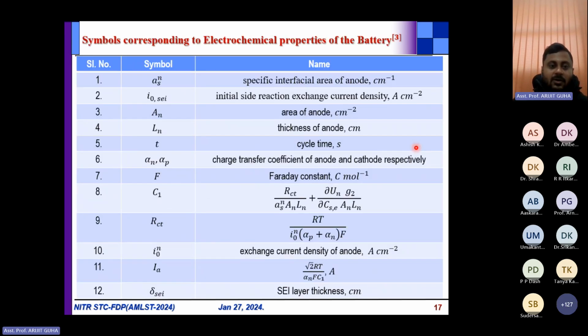Okay. Now these are some of the symbols which are associated. Now see, we have only 400 initial cycles of data, partial charge discharge. So that will roughly be, you can see, the state of health from 100 to 96%. Okay, 400 cycles of data. Now if we have to depend on a very small amount of data, we actually need some extrapolation. To extrapolate those characteristics, we need a battery electrochemical model behavior, so that with some partial information we can tell that this can be the trend.